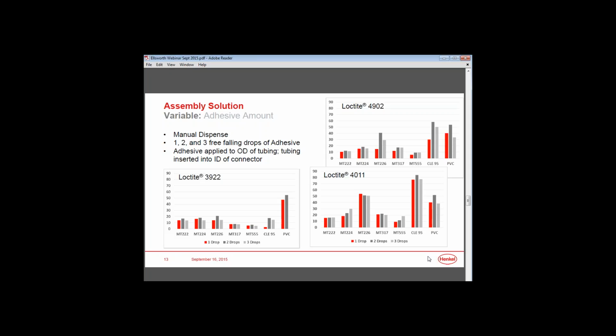So you'll see, based on this testing, that the ideal drop size we selected was 2, but you'll note that there isn't a huge difference in the results based on the adhesive amount size. You'll note that as we get into adjusting the gap, that's where adhesive amount can be a cause for differing results. But here you could be pretty confident that adjusting the drop size didn't have too much of an effect, and so from here out we selected 2 drops on the assembly.